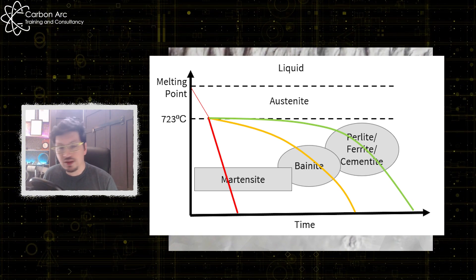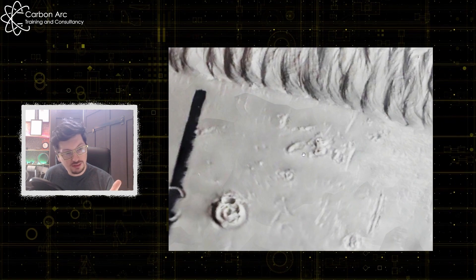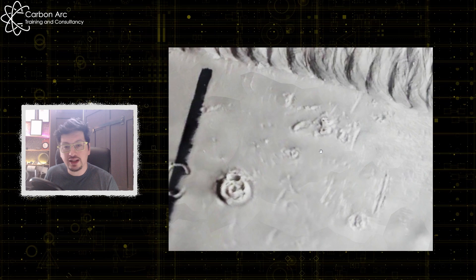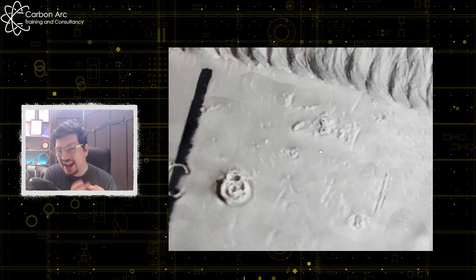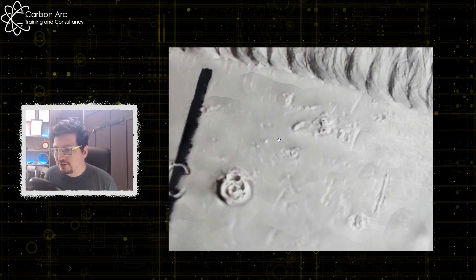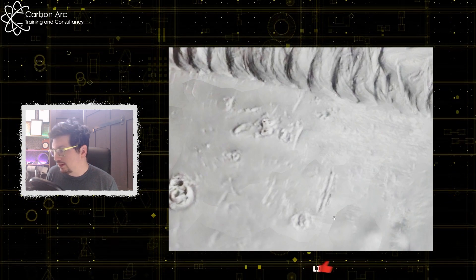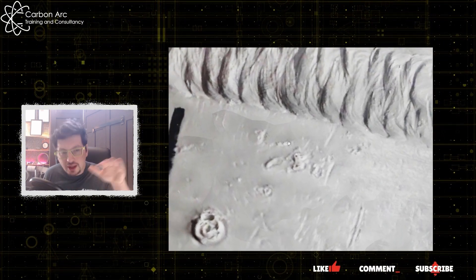So now we've looked at the TTT diagram, we can see our arc strike and how we identify it. It's this molten sort of weld metal area outside the weld zone. We can see that this is different from mechanical damage which is right next to it because we've got that melting and then build up in the center.